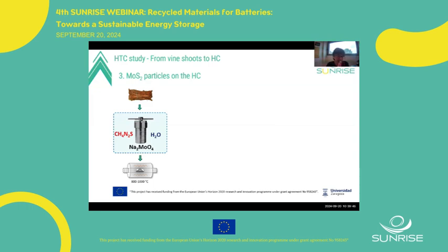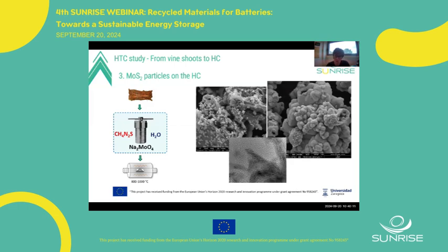In this case, we added molybdenum disulfide particles on the hard carbon surface through performing a direct hydrothermal carbonization of the biomass with water, but also with thiourea and sodium molybdate, in order to introduce these particles on the surface, since they can generate redox reaction and also intercalation with the sodium ions to improve the battery performance.